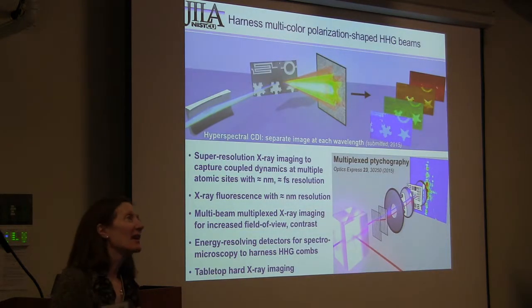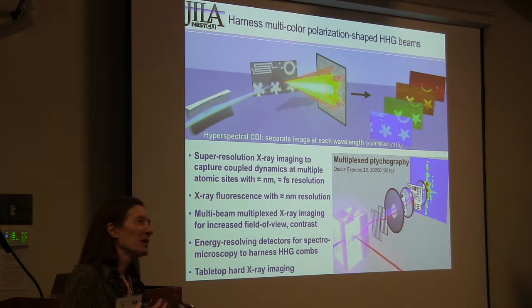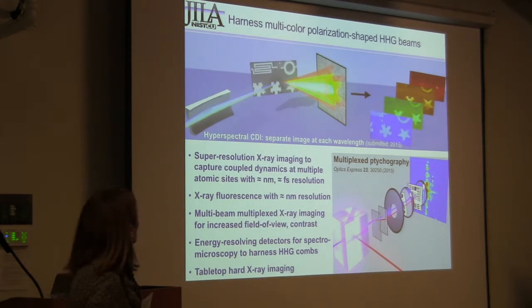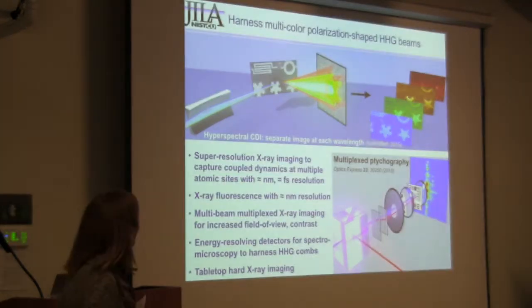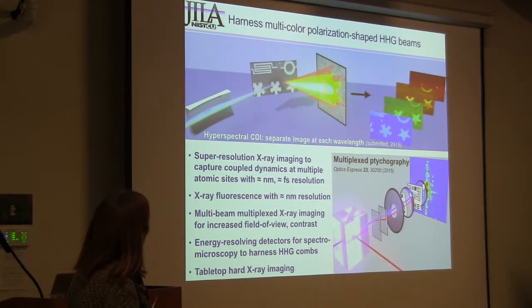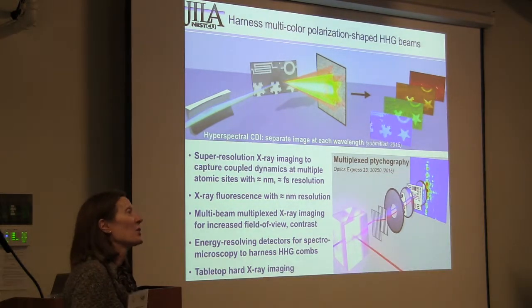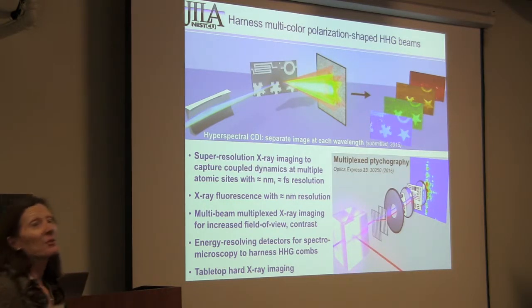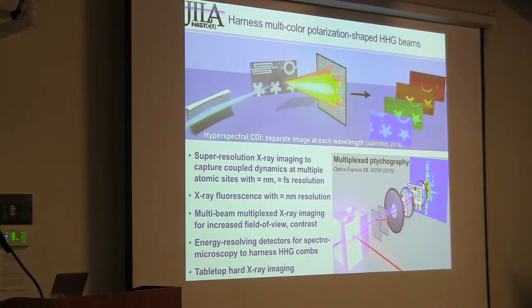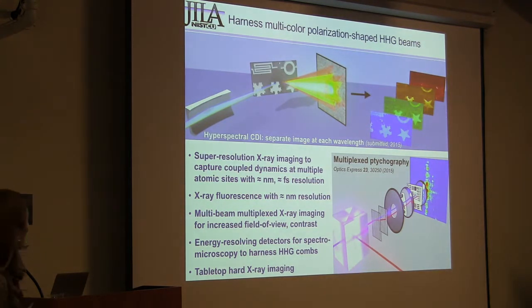But the neat thing is that, as we do with spectroscopy and X-rays, we can take advantage of the fact that you've got multiple colors. The algorithm is smart enough that if you shine more than one harmonic order, you can retrieve an image of each color. This is just a demonstration for now, but you can see how that would be very nice for a composite sample. Particularly if you can do that in real time, because you can actually see if there's energy flow, charge flow, spin flow.